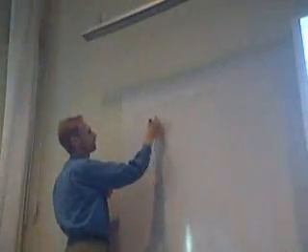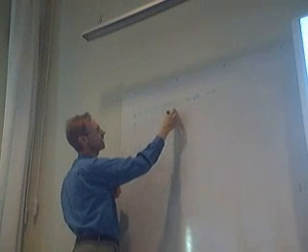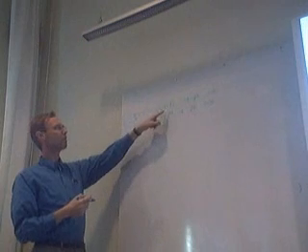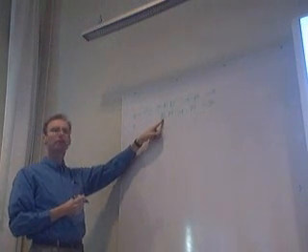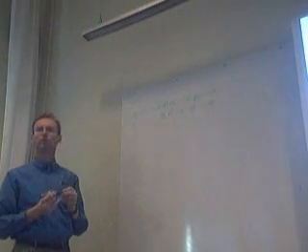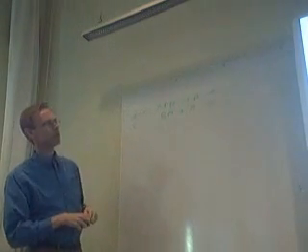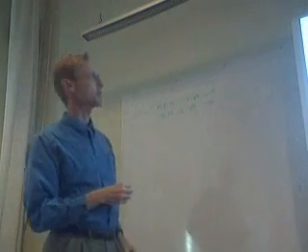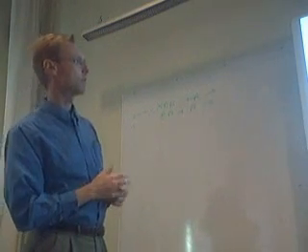A higher order Markov process would be much more complicated, because you'd have polymers that would end in AA, you'd have another set of polymers that end in BA, and this second order Markov process would remember the stage before as well. So these two reactions would happen with different rates. That would be a much more complicated system. And actually I don't think we need that sort of process in order to model our results.